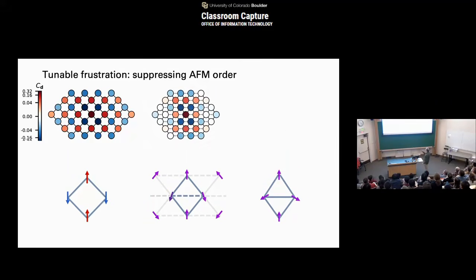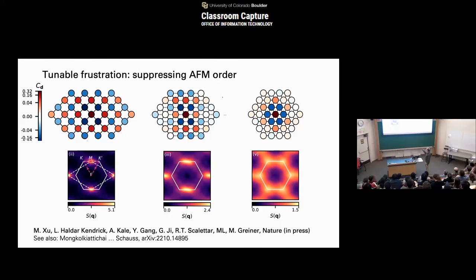And if you do this, we can then image the spin patterns that we get at half filling. And you see here for the square lattice, we get our antiferromagnet, as we had it before. But then as you turn on this diagonal tunneling, the geometry changes from an antiferromagnetic pattern into one where you have a triangular symmetry or hexagonal symmetry here. And you also see overall, of course, antiferromagnetism is being suppressed here. That's what we are interested in the context of Nagaoka magnetism. We can Fourier transform these spin-spin correlation functions, and then you can nicely see the spin structure factor here, derived by the Fourier transform of these correlation functions that we can then nicely measure directly in the quantum simulation.